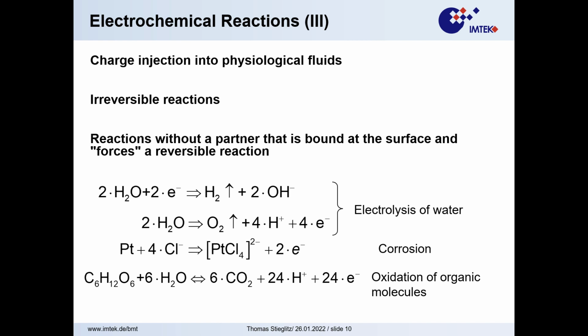That means if you damage your electrode in one half of the stimulation pulse, then it deposits on the other half. And if you would do a characterization, just an overview characterization, let's say, oh, my electrode looks really good, nothing changes. And then from one pulse to the other, you say, oh, no, it failed. That's then the point where really the interconnection line or whatever has completely corroded. So you might have an electrode, but there's no contact any longer, or you have lost your whole surface area or something like that. That's one of the disadvantages of platinum, that it's really hiding a little bit its corrosion with that mechanism. And if you would do it even worse, then you could oxidize organic molecules. And this is nothing we want to do with electrical stimulation, that we jump into whatever metabolic circuit and oxidize whatever is around.